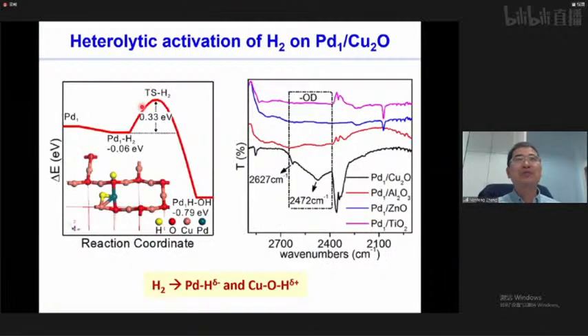And why we will be able to use this palladium +1 for the reaction, because this palladium +1 is still active for the hydrogen activation. Because for this copper 2 oxide, they have strong basicities. So the hydrogen can get activated on the palladium through heterolytic activation pathway to form hydrides on palladium and proton on oxygen on copper 2 oxides. And we do have the FTIR evidence to prove this.